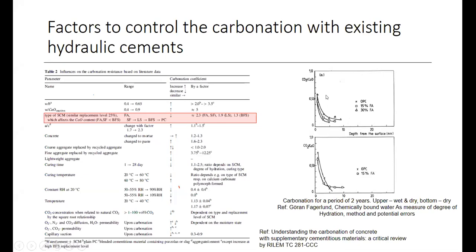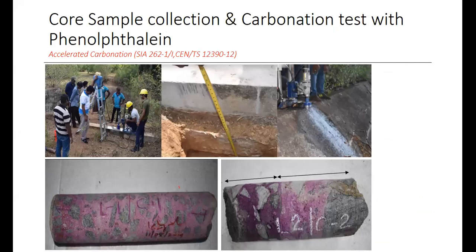You can see initially in the wet and dry cycle, OPC delivers better results compared with a higher amount of fly ash. The reason is that fly ash consumes more portlandite, or calcium hydroxide, which came from the cement hydration process. But OPC has more calcium hydroxide, which was not consumed by other minerals. So it can react with carbon dioxide to neutralize, or to form calcium carbonate inside the concrete. That is the reason. So by applying those theories, we have done research, actually one good piece of work with NBRO.